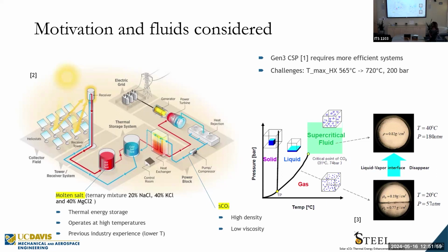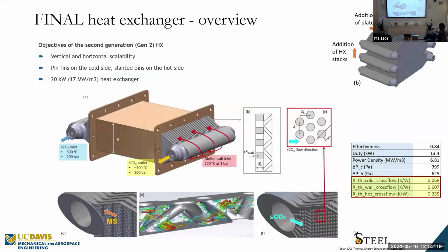I had a question. On the molten salt part, that seemed to be the one with the higher thermal resistance, right? Were you able to do any kind of optimization on that side? Like you showed some pins. Was there any optimization or analysis done on this side? Not strong optimization, but we looked at a few cases, because when you keep adding these fins, you increase the pressure drop, and especially with additive manufacturing, you cannot really guarantee that your final product is going to be exactly the way you design it. So you might have some more clogging. So we try to design these fins so that we decrease the thermal resistance, but still don't end up with a prohibitive pressure drop.